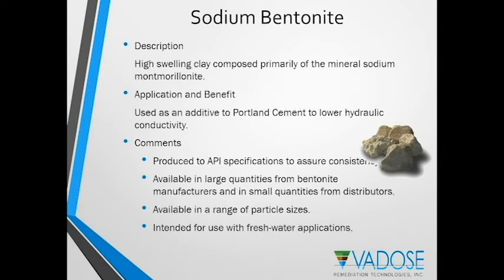The next amendment that's used in solidification and stabilization is sodium bentonite. This is a high swelling clay that's composed of the mineral sodium montmorillonite. It's often used, or sometimes used, as an additive to Portland cement mix designs to further reduce the hydraulic conductivity. It too is produced to specifications consistent with the API, American Petroleum Institute. It's available from various manufacturers around the country in a wide range of particle sizes for various applications.